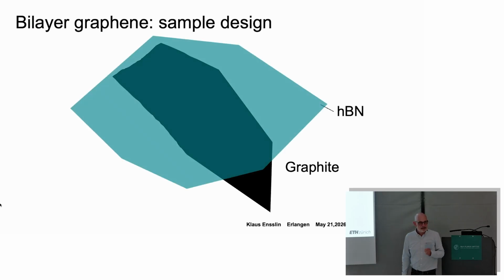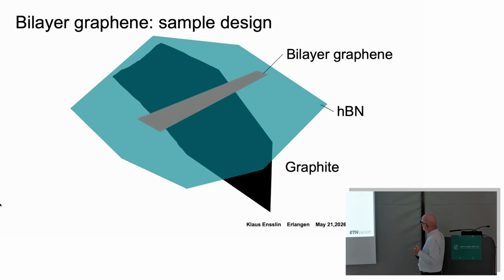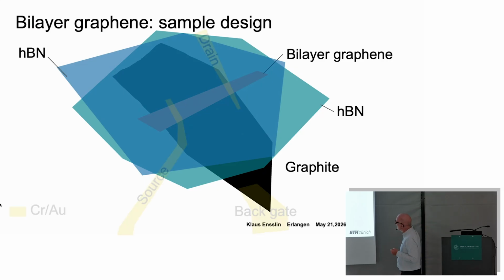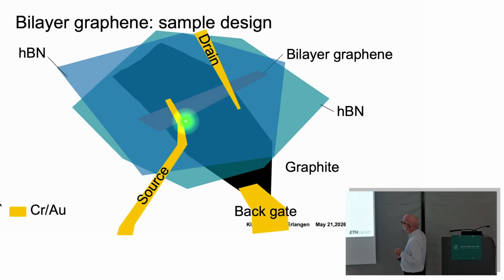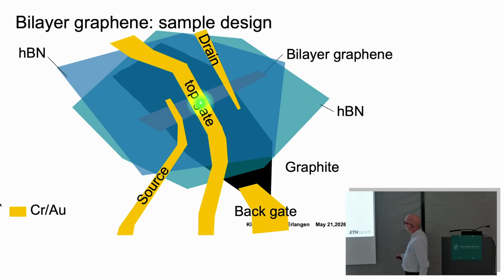Then we cover this with hexagonal boron nitride, another one of these 2D materials that you can stack. Then you put a piece of bilayer graphene on top, next hexagonal boron nitride. Then you etch down a little bit, and you make these ohmic contacts to this layer of bilayer graphene, and then you put a top gate in the center. And now if you apply a voltage between the top gate and this back gate, then locally you create your electric field, and locally you can make a large band gap. And because you have two gate voltages, these are two degrees of freedom, so together they give you the size of the band gap, and they give you the position of the Fermi level in the band gap.